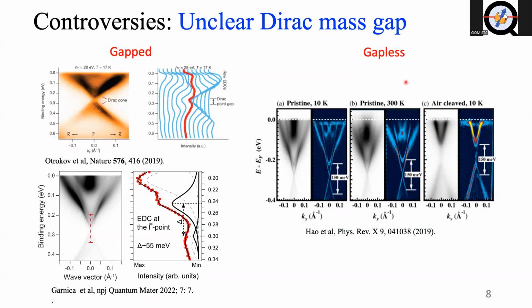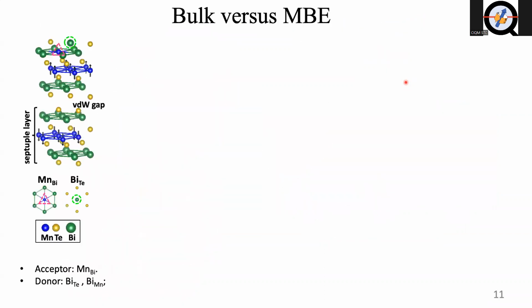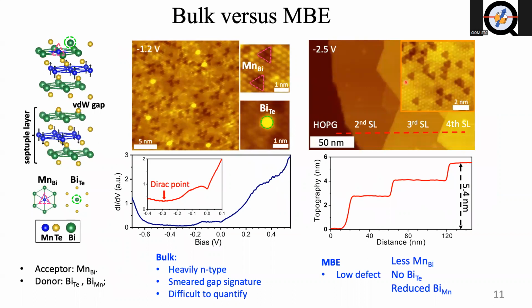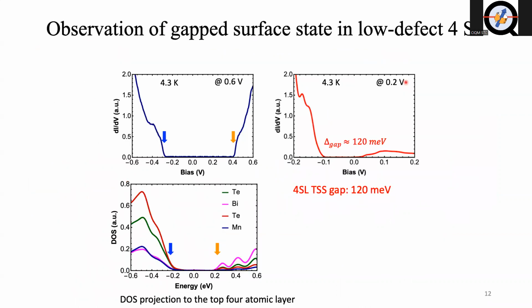Yeah, so I guess the improvement for us is we can eliminate the amount of defects and get a really intrinsic sample. So you can see that the Fermi level position is inside the gap. And this density of state really goes to zero, meaning there's no density of state. That means there's a gap. So the biggest improvement is actually from the MBE grown result. So you can really get intrinsic samples.